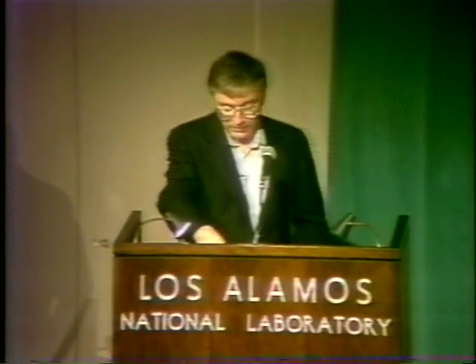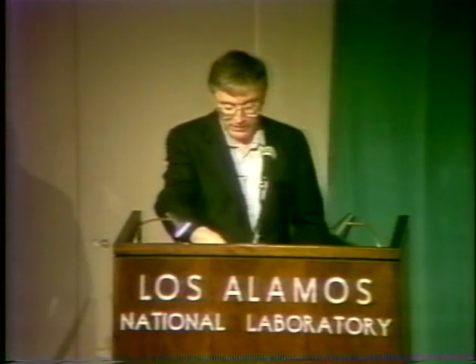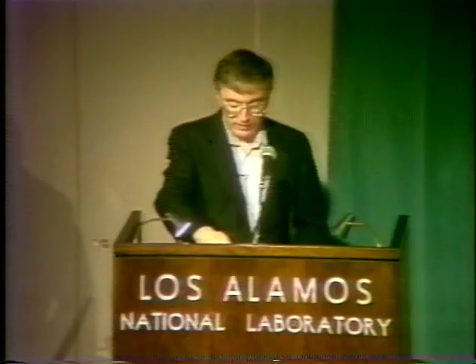The baseline experiment that we've done the most with has been a dead palladium rod, one that never got started because of some metallurgical reasons probably, or some surface effects. And that rod, in the same cells, under all the same conditions, gives absolutely the same amount of heat out that you put in. But the active palladium rod that had been acting in D2O does not give that in plain water. It gives a slightly higher amount of heat out.